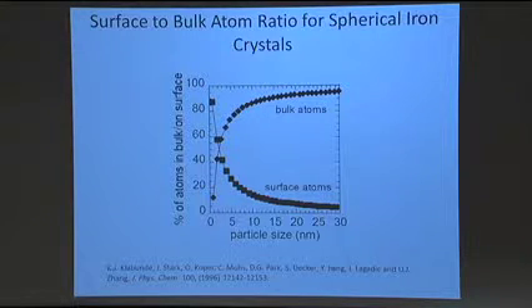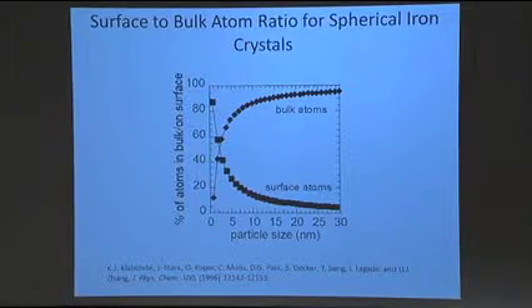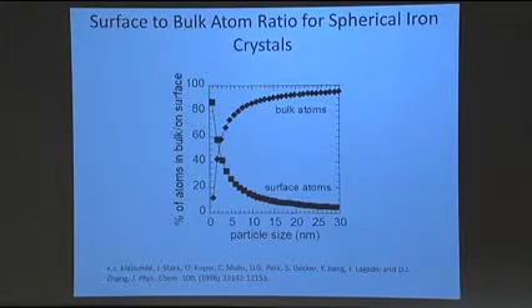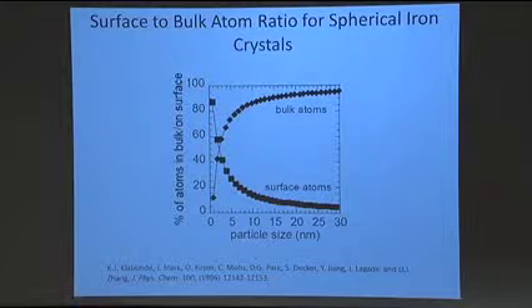Okay, so let me show you some of these characteristics that we want to make use of. And I started to mention these in the previous slides here. This is an example where I go back and look at a nanoparticle, and what I told you was that as I shrink the size, more and more of the atoms are located on the surface. So what I'm showing you here is some iron crystals, with a plot as a function of particle size of the number of surface atoms versus the number of bulk atoms.